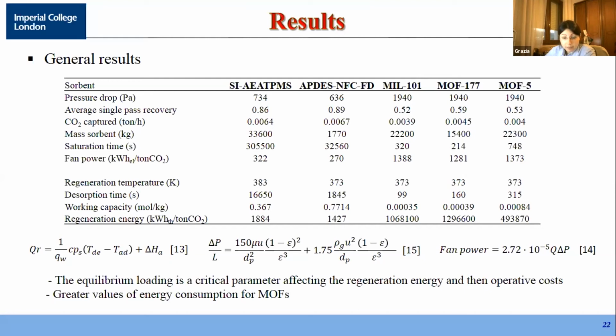Also, we can see the great value of energy of regeneration for metal organic frameworks, and this is due to the low working capacity, then due to the lower equilibrium loading, that is a critical parameter for adsorption, influencing the energy of regeneration and then the operative cost. Overall, we can see higher values for energy consumption for metal organic frameworks compared to the amine functionalized sorbent.